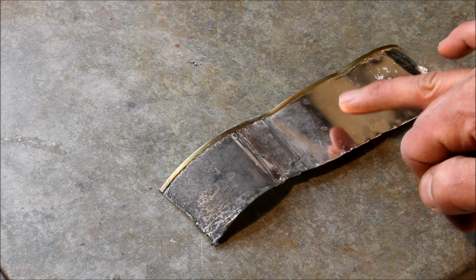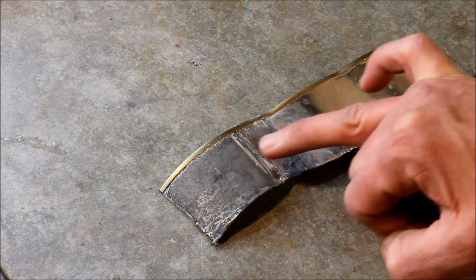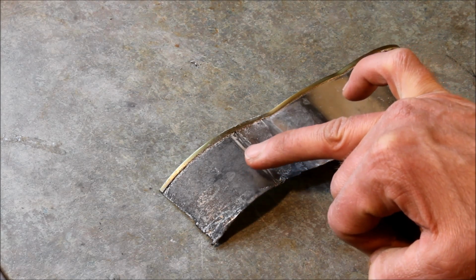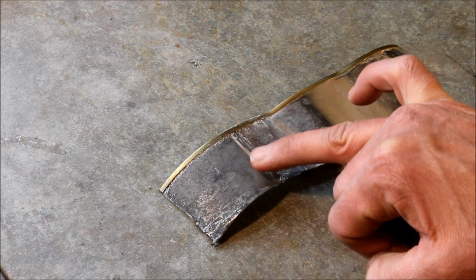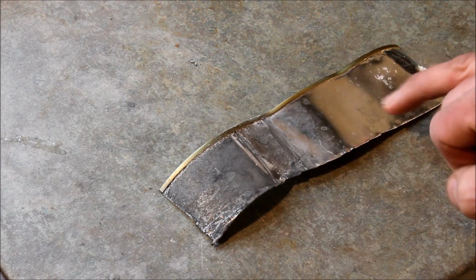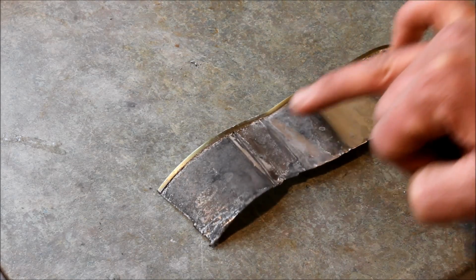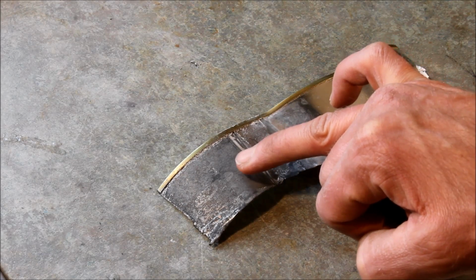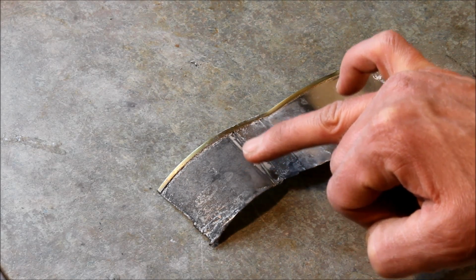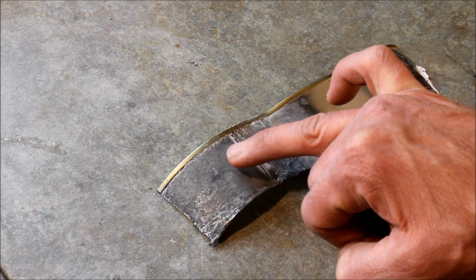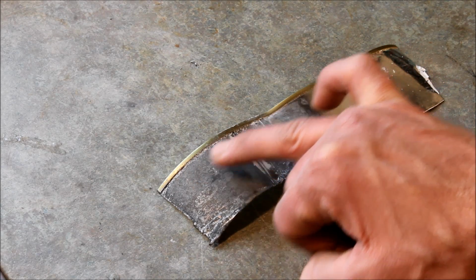Now this is just a bit of scrap steel plate which I've deliberately burnt the end of here by plating it at far too high a current so that you know what the symptoms are. So this is what bright zinc plating should look like. I've burnt this end by plating this at probably 5 times the current it really should have had. And you see you get these really ugly looking, dark, dull grey deposits.